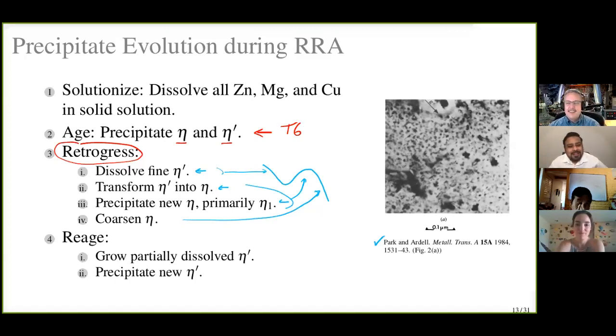So as you say, as the eta actually coarsens, the hardness reduces. So there is an intricate relationship with the grain size. Well, the grain size doesn't really change very much because we're at too low a temperature for grain growth, and we still have enough precipitates to pin the boundaries. So this coarsening is really just the precipitates themselves. And once we go past the second peak, once the precipitates are coarse, you can't uncoarsen them unless you go back and solutionize everything.